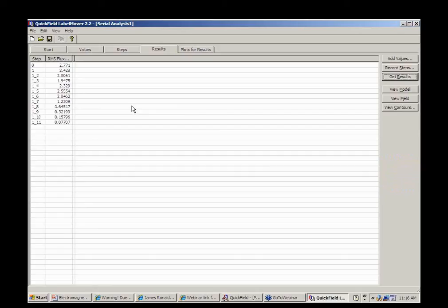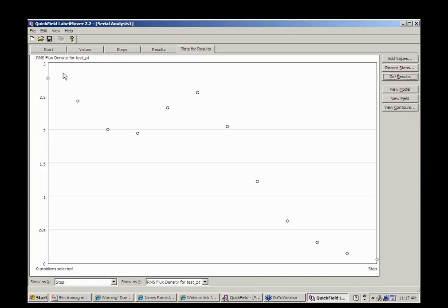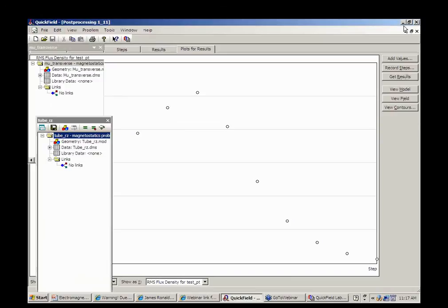Okay, now we're approaching 100 kilohertz, so we can see our results. And we can see how the flux density inside of the sphere is actually changing as a function of frequency. It begins to decrease initially, then it rises again, and then it decreases as we're going to higher frequency. So this would be relatively ineffective at shielding low frequency fields if you were making highly sensitive magnetic measurements at low frequencies. And an iron sphere is probably not going to be your best choice.